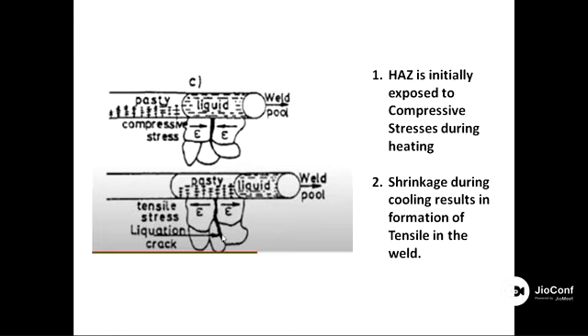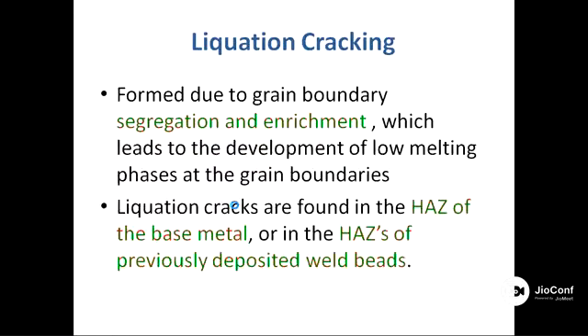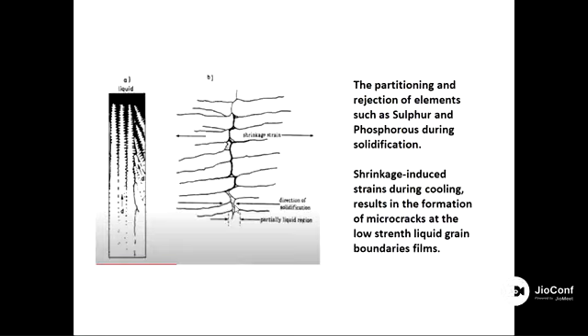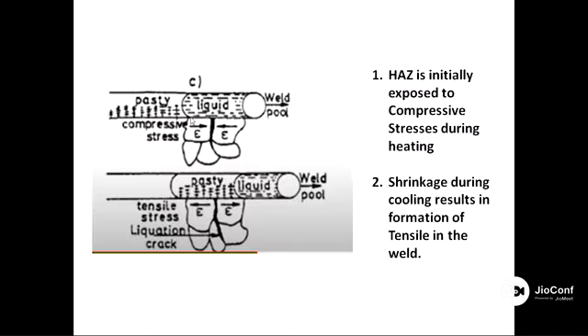And because of the tensile stresses, this figure, right? Because of the tensile stresses, the cracks are produced whenever there is a presence of low melting point eutectics in the grain boundary. So they are not going to support the strength, but they are going to separate the grains from each other at the grain boundary, right? At the interface. So you will end up with the process of cracking.